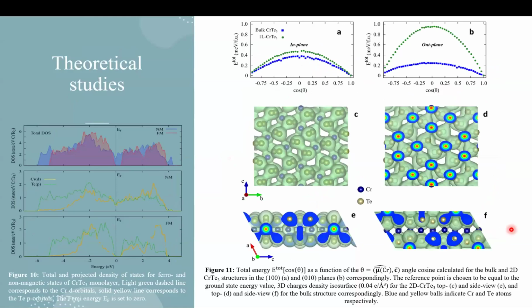So the theoretical studies showed us that we were able to retain the long-range ferromagnetic ordering even in the 2D limit for quite some time. And we observed that there was a band gap opening in the structure also, which is usually observed in all 2D materials. And this helps us retain charge when used in the nanogenerator.